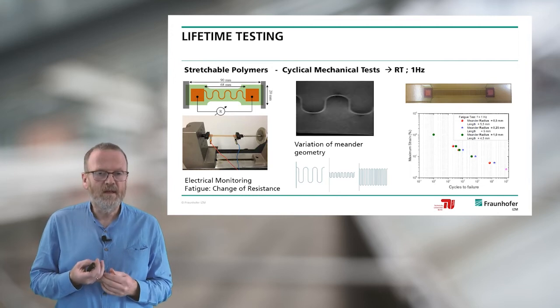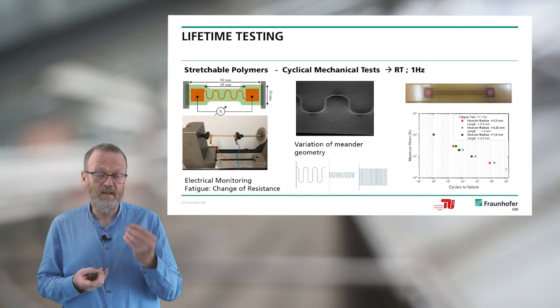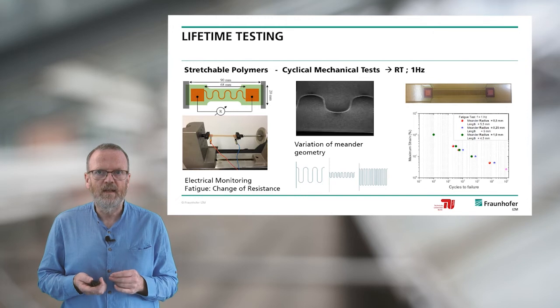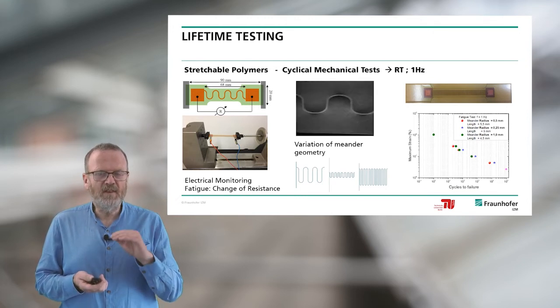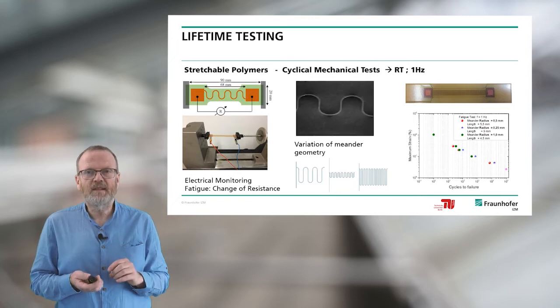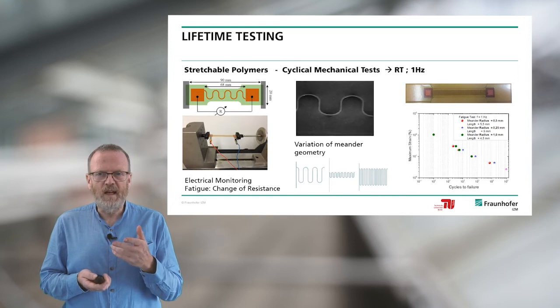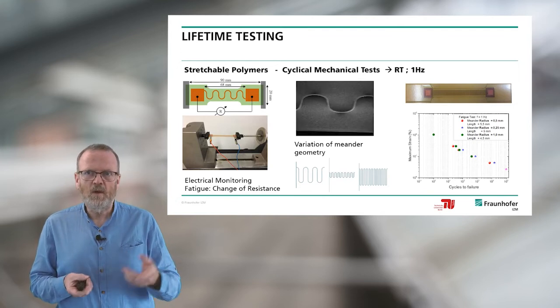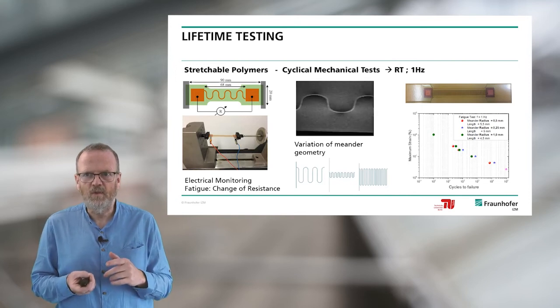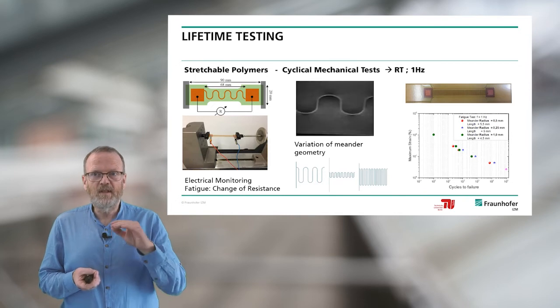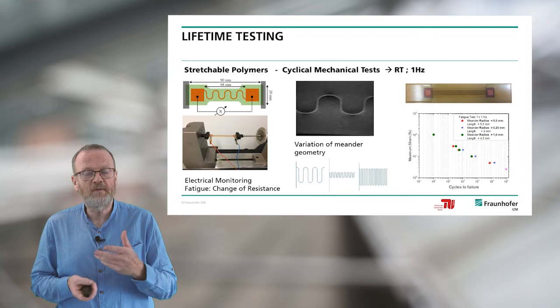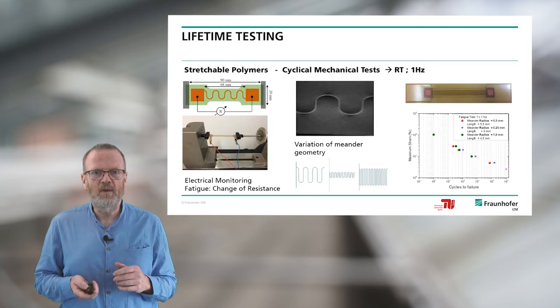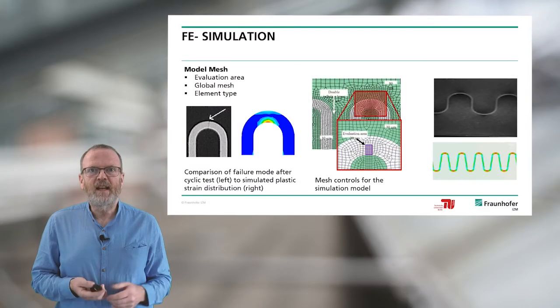On this slide you see some results. On the left side is the typical geometry — the combination of polyurethane and copper — and you can see the loading tester. In the middle you see the cycling sample with the meander structure; there is a change of color from dark gray to gray, which is the first sign of changing material properties. The diagram on the right side shows the maximum strain calculated by simulation tools versus cycles to failure NF, with the different geometry points used to analyze parameters C1 and C2.